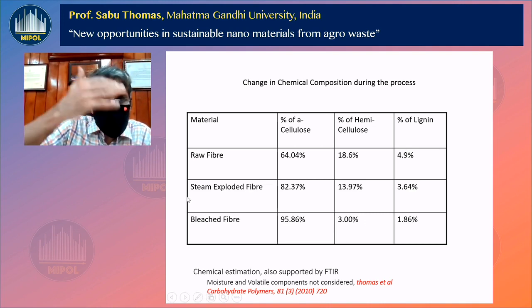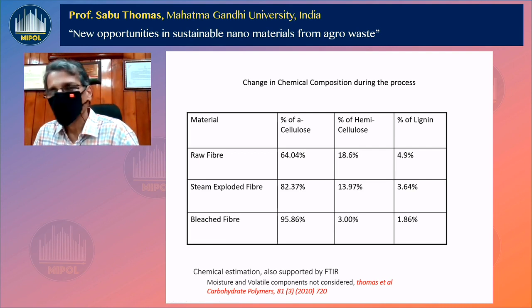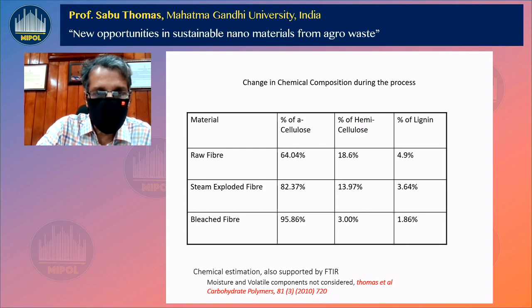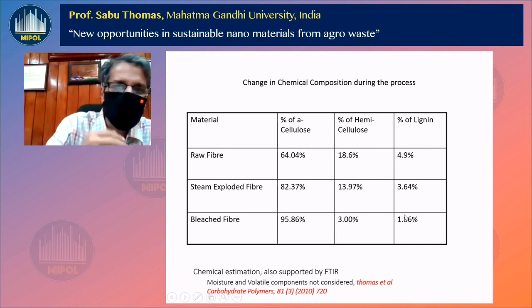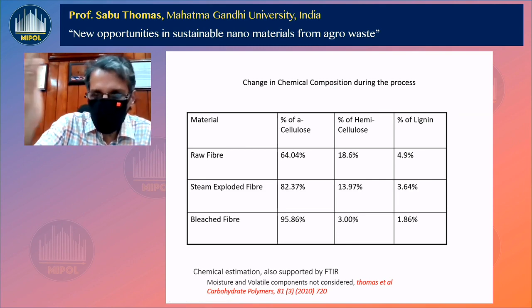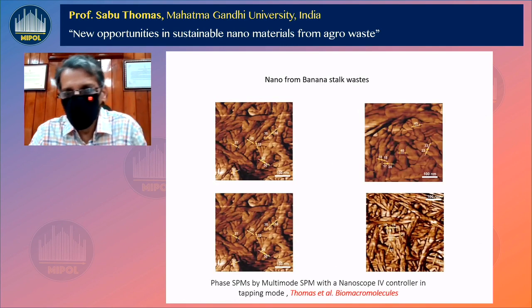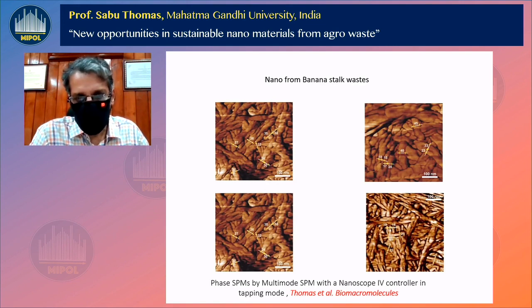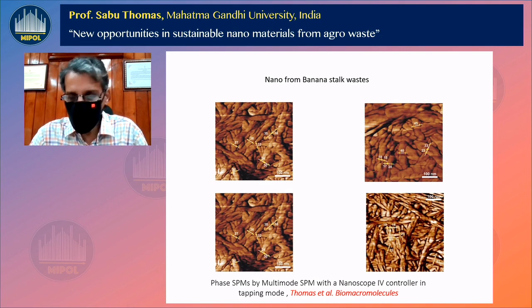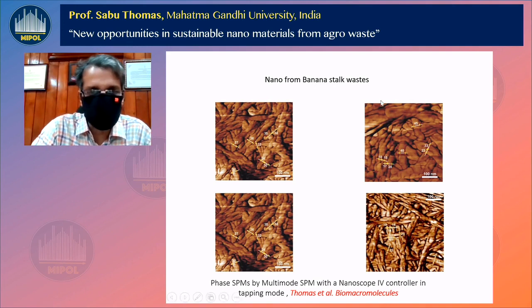As you treat this fiber with acid, at the end of the day you get something like 95% nanocellulose, and you remove hemicellulose and lignin. Just to show you the enrichment process, you remove lignin and hemicellulose progressively. I want to show you another very interesting slide from my former co-worker, who is right now in the US doing a postdoc. He made beautiful work. He made lots of nanocrystals from banana stalk. He collected the banana stem from the agricultural plantation and went for acid hydrolysis with strong acid. He made beautiful nanocrystals.